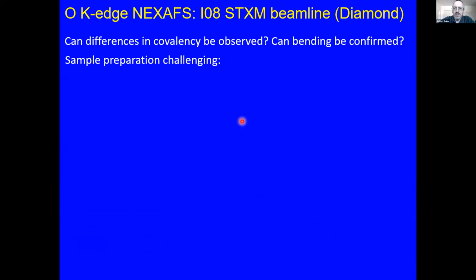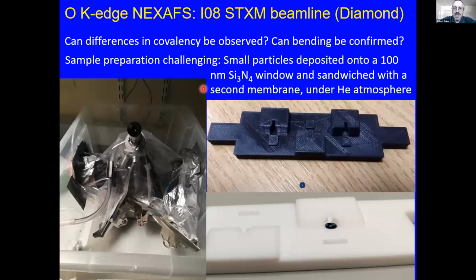The problem was our sample preparation, and this is the hardest thing I think my PhD student has ever had to do in his life before. So we had to just put small amounts of sample on these TEM grids, and then for radiation protection reasons, sandwich them with a second membrane. This had to be done under a helium atmosphere to make sure we didn't have any oxygen in the sample from the air. We tried a number of ways to be able to do this, because sandwiching these using epoxy resin was really, really tricky.